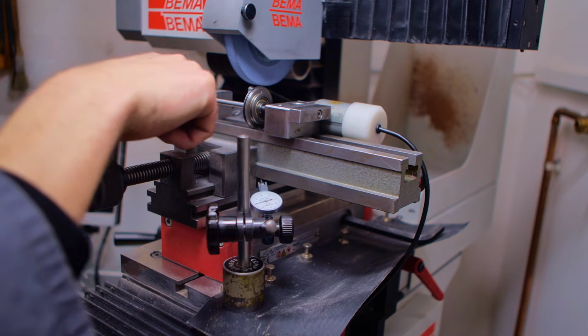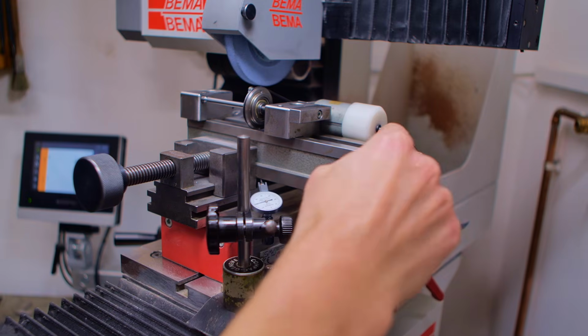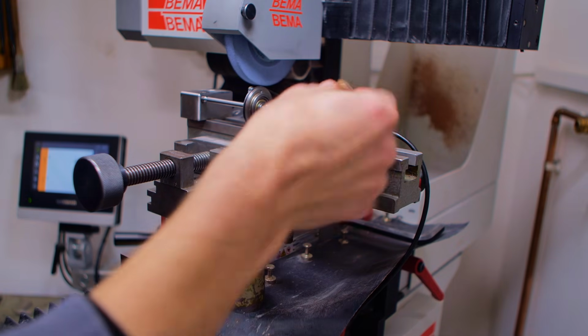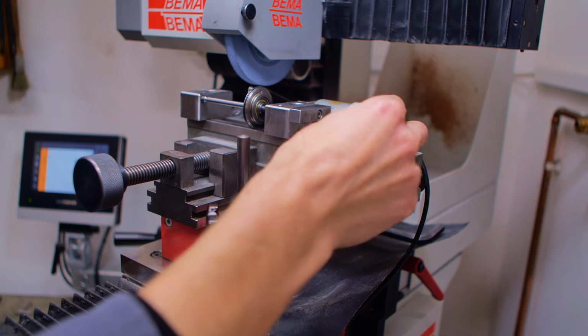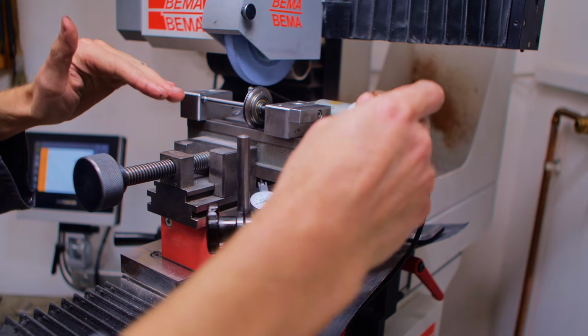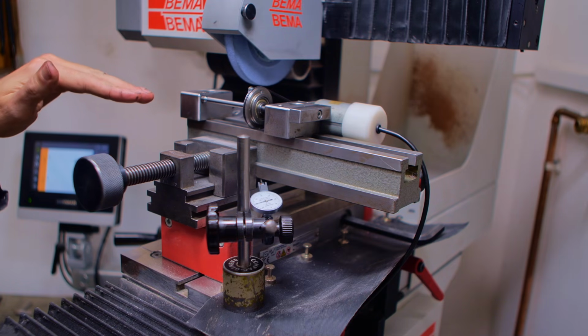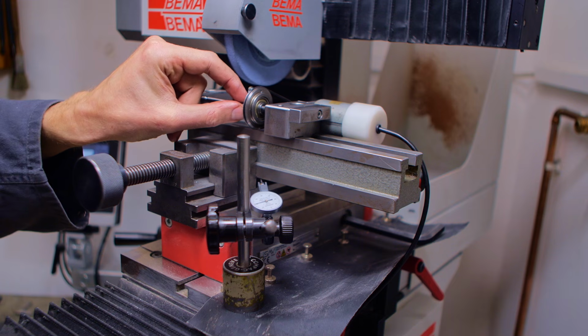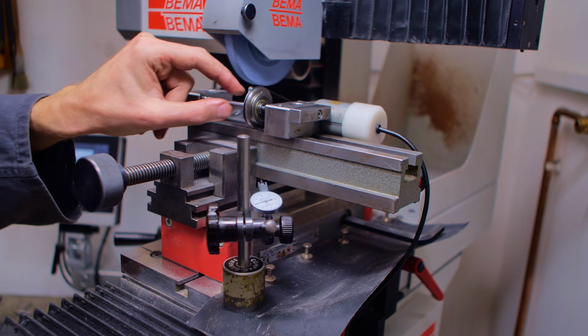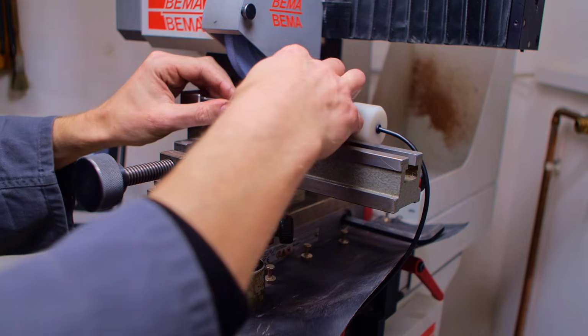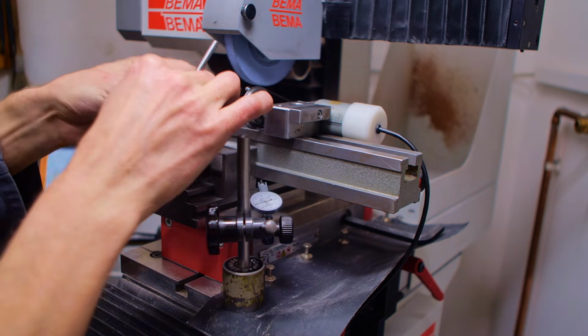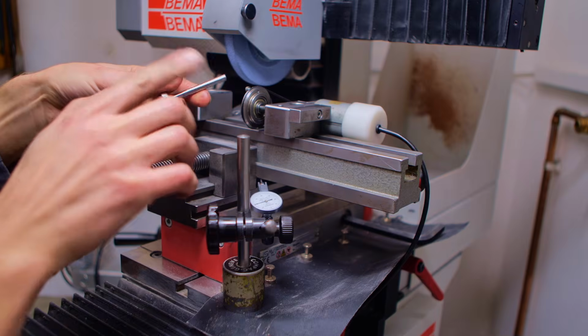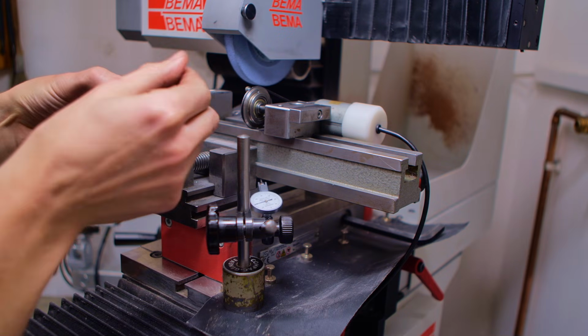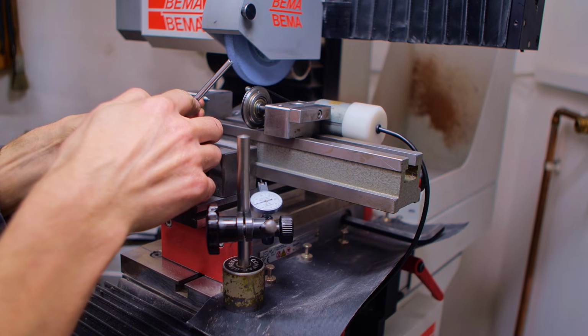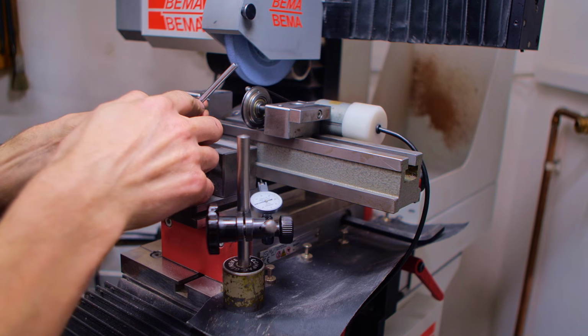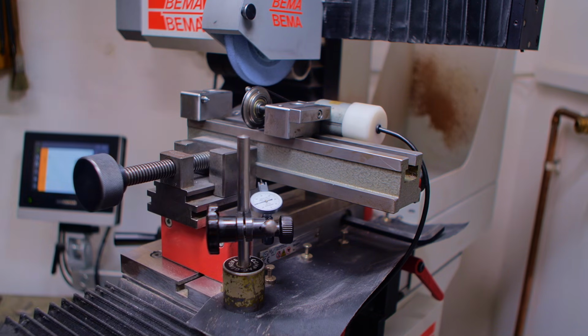Holding it in a grinding vise, and I have a dial test indicator here, so I took a brass piece or copper piece and I knocked the fixture around until it ground parallel. Well, not parallel, 8 micron taper. Smaller here, bigger here. So I ground this arbor here, just between centers. This is soft steel. This has only to hold up for one part. It's 6.008 here and 6.000 here.